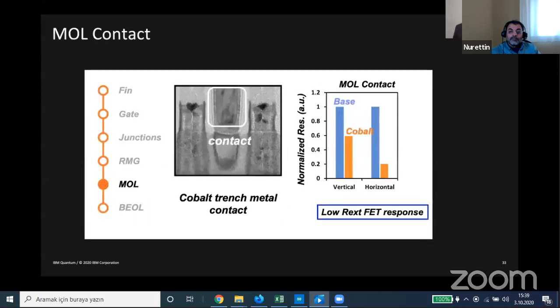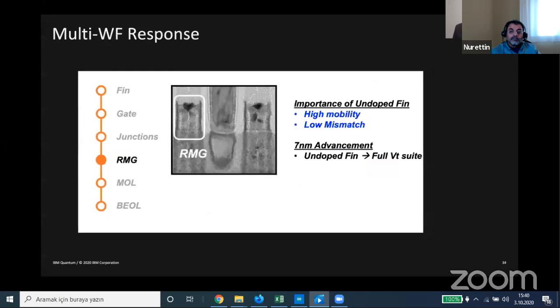Next, the middle of line contact, the fill material was very important. We introduced here a novel material, which was cobalt for this layer. And here you can see we lowered the vertical resistance and horizontal resistance significantly, and this resulted in a lower FET resistance.